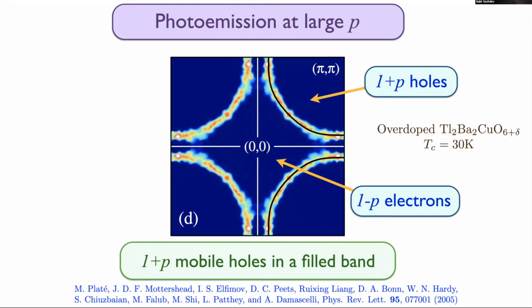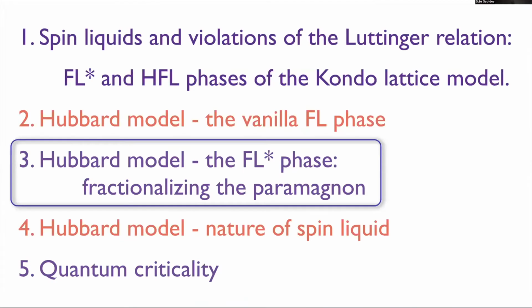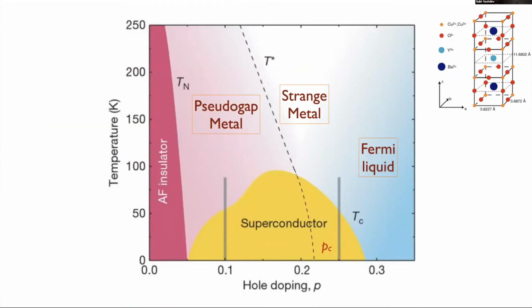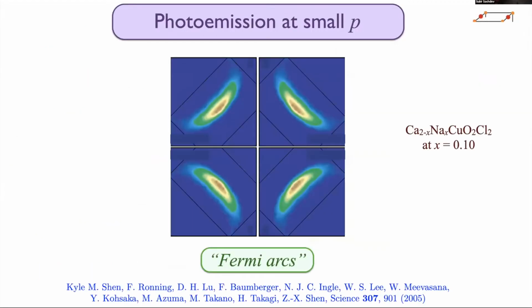All right, so my focus here is really not on this, but I want to now go to the underdoped side. So on the underdoped side, which is what you see in the photoemission, well, this is one very famous paper of ZX's group in an underdoped cuprate. That big Fermi surface has disappeared, and you have these features that are sometimes called Fermi arcs. But also very importantly, you have a gap in the antinodal region here. There's no low energy excitations near the Fermi surface.